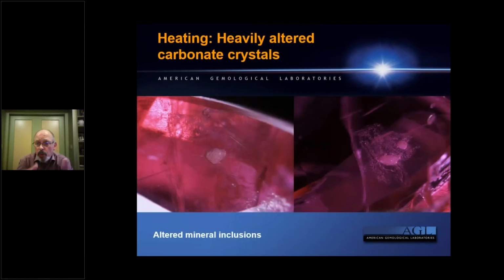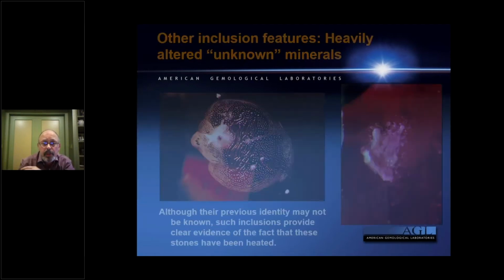So what do you start to see when you're heating also at relatively higher temperatures? You're seeing inclusions which are much more readily recognized as being altered by heat. So these were calcite inclusions. And so you see they've gone through thermal shock, they're translucent, they're white, they're heavily fractured. There's clear evidence. Again, you see this, you're able to make a definitive statement that a stone has been heated. Most minerals at the relatively higher temperatures are going to start to alter.